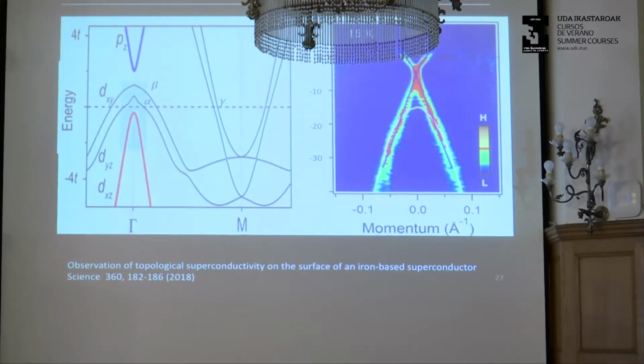Now, what about the surface state? So it's these two bands, the band labeled PZ and this band here. These are the ones that are supposed to, as you add more tellurium, basically this band gap is supposed to close and reopen, and when it reopens, you're expected to see a surface state right here in this gap. And in fact, initial ARPES studies, just last year actually, showed that there might indeed be a surface state. So here's data, this is ARPES data. This band here is this band, and you can see a Dirac-like dispersion that lives right here in this gap. Okay, so this is possibly the Dirac surface state.